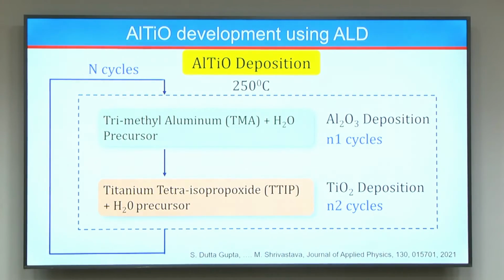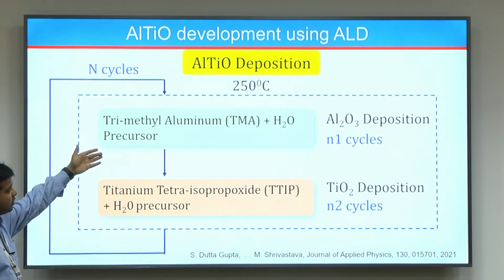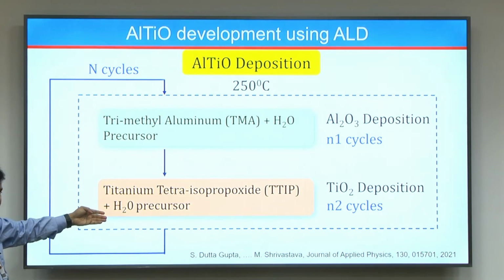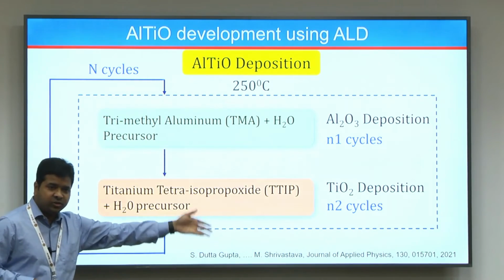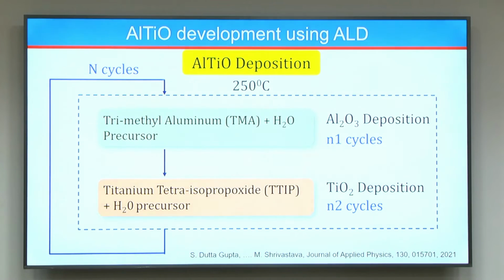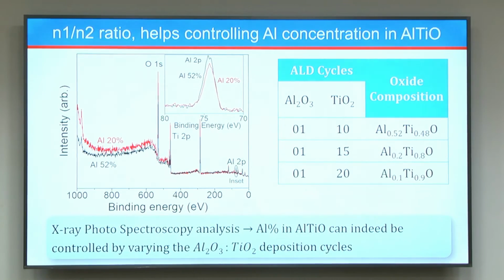And in terms of the gate oxide, how we achieve it: we basically did a cyclic ALD deposition of TiO2 and aluminum oxide. So you can program this in the ALD chamber. You have a few cycles of aluminum oxide deposition, and in the same chamber you have a few cycles of TiO2 deposition, and then you repeat it, right. So in this way you alloy TiO2 with aluminum oxide, and depending on the ratio of N1 and N2 here, you can control the percentage of aluminum in the overall stack that you develop, right. So if you see here, depending on different cycle configurations, the percentage of aluminum varies. So we can control all the way from 0% when there is no aluminum oxide to 50%, 52% when it is done in equal proportion.